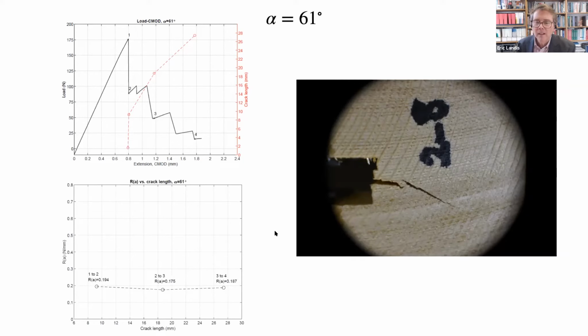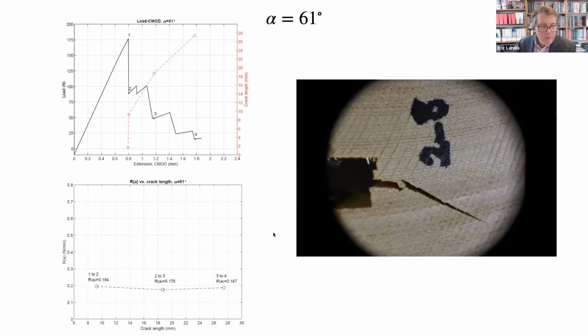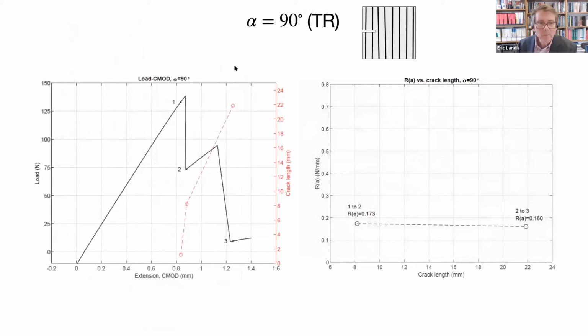Now, what we found of interest here is that the early wood, late wood orientation is, again, 60 degrees relative to the initial crack. But if you look closely, it's a little hard to see because we're seeing artifacts of the saw cut. The rings are in this direction, and see the crack, it just turned and goes normal to the rings, which is directly in the radial direction. So this implies now that the radial direction has less resistance, even than going straight.